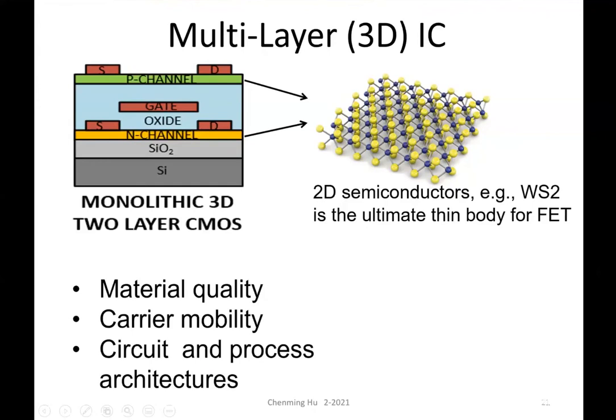And you can grow a single crystalline film of this on silicon substrate, 12-inch, and then transfer it onto silicon dioxide. And you can do this transfer many layers. Here it shows 2 of these layers, but you could have 4. And this then is how you make the monolithic 3D ICs.